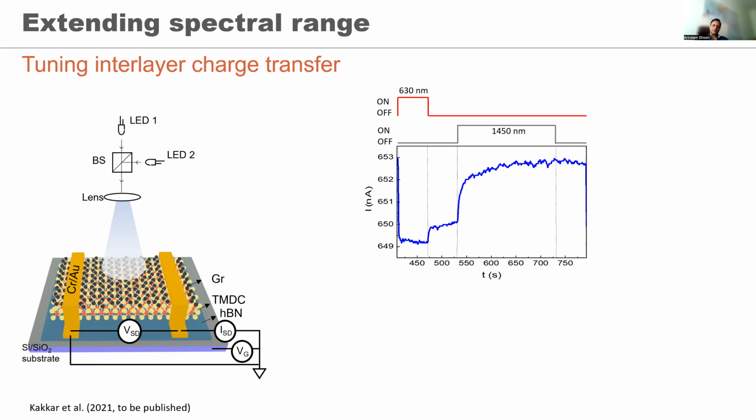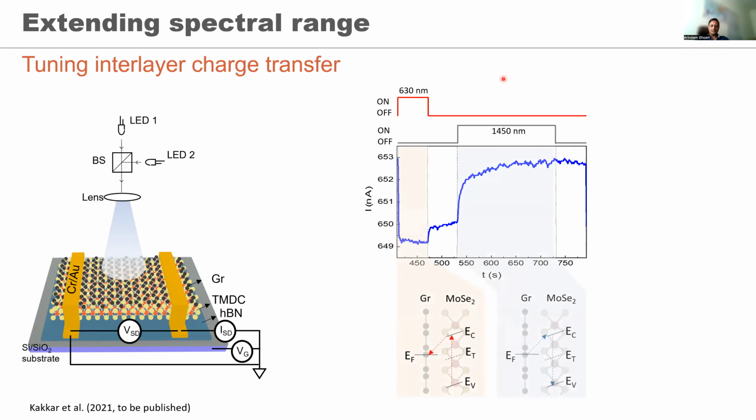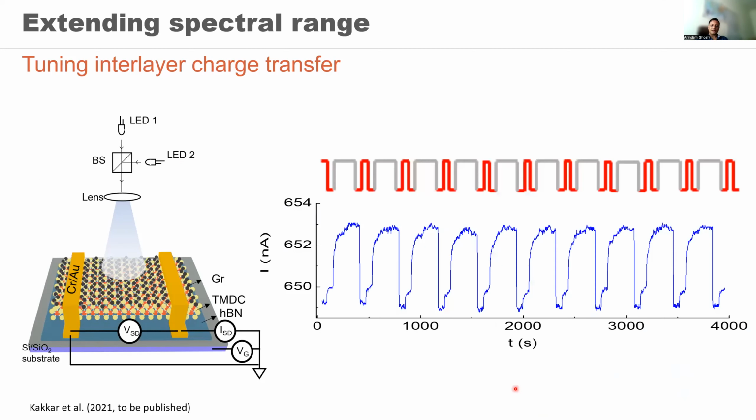So that makes this whole system now sensitive to infrared radiation, which is much lower energy photons than the chalcogen band gap. This is essentially what is given, and you can do this many, many times, and you can create a beautiful detector, a memory, whatever you call it, of infrared.